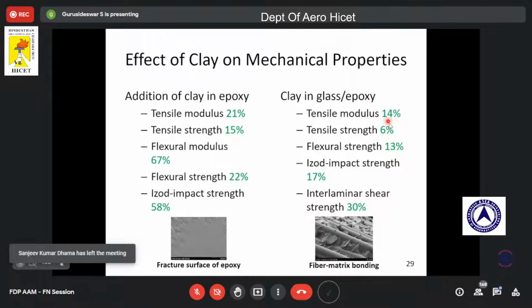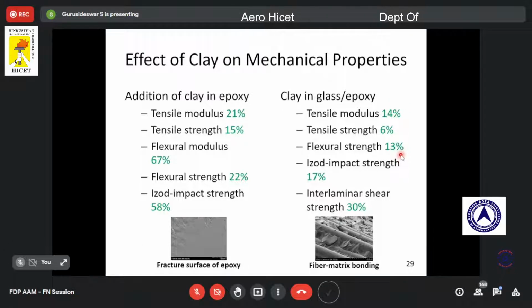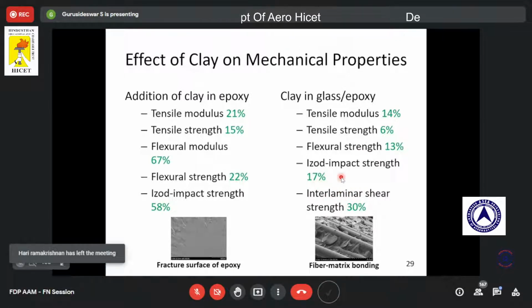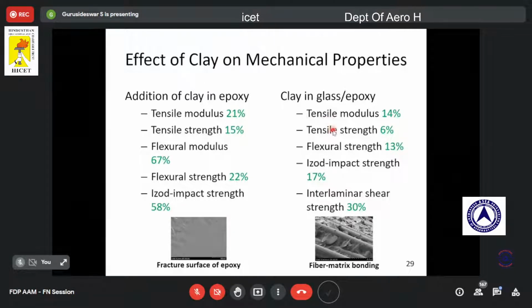And one more thing I want to emphasize on this data. One can observe there is a limited improvement in tensile properties, but there is a major improvement in the interlaminar shear strength and impact strength. The reason is that tensile properties are dominated by the fiber, where the fiber plays a major role. The matrix may not play a major role. Whereas in the interlaminar shear strength or impact strength, the matrix plays a major role.